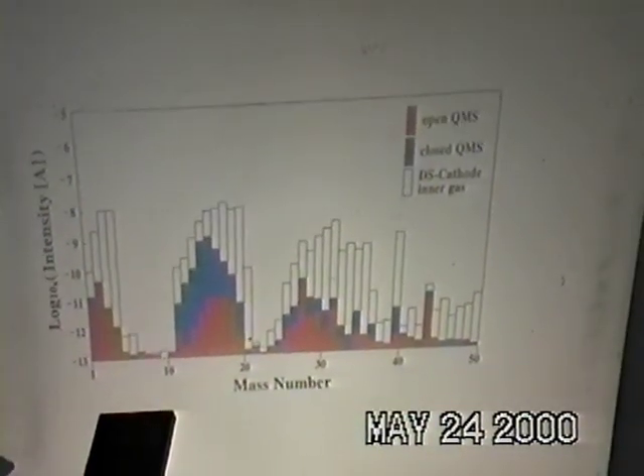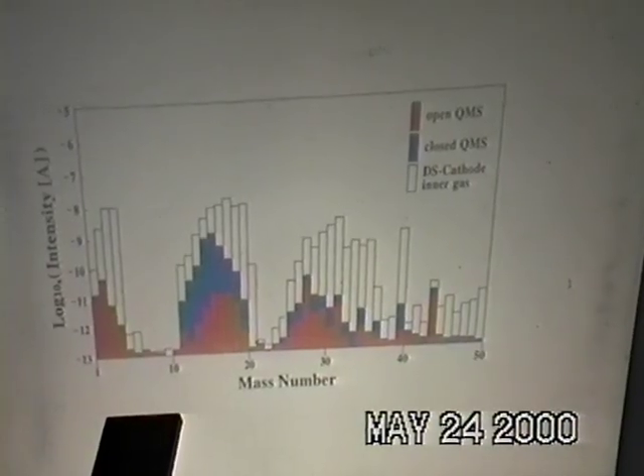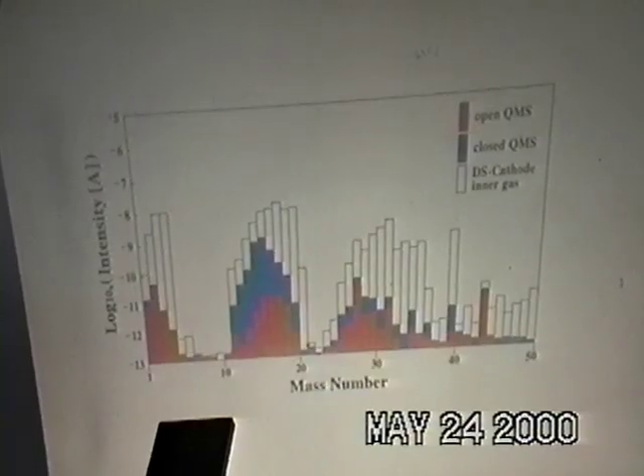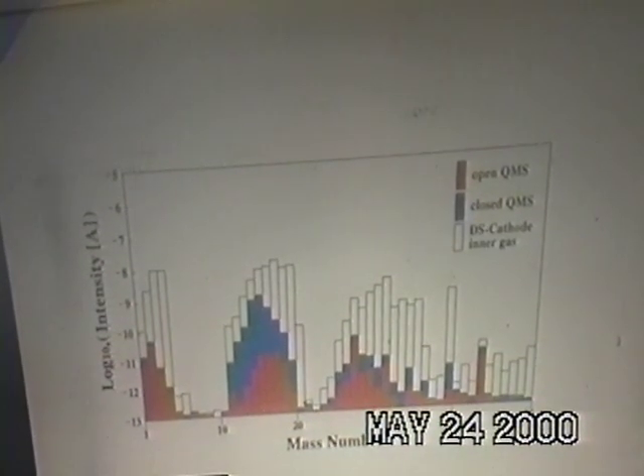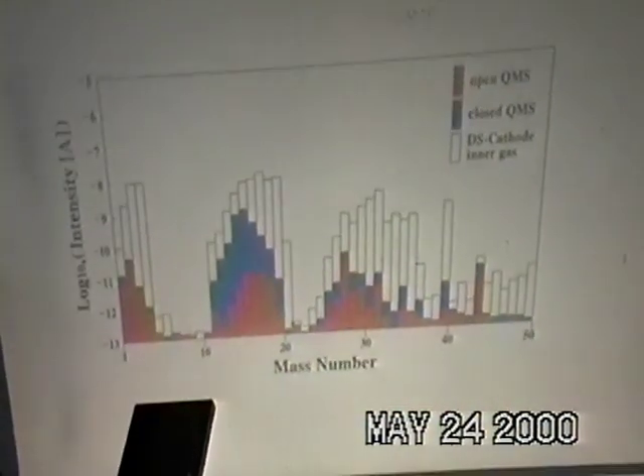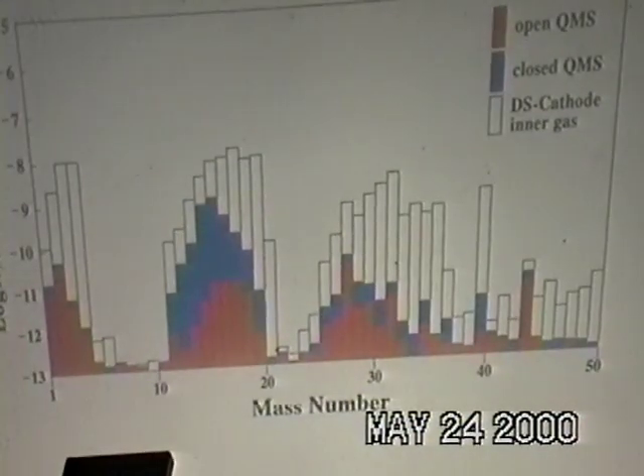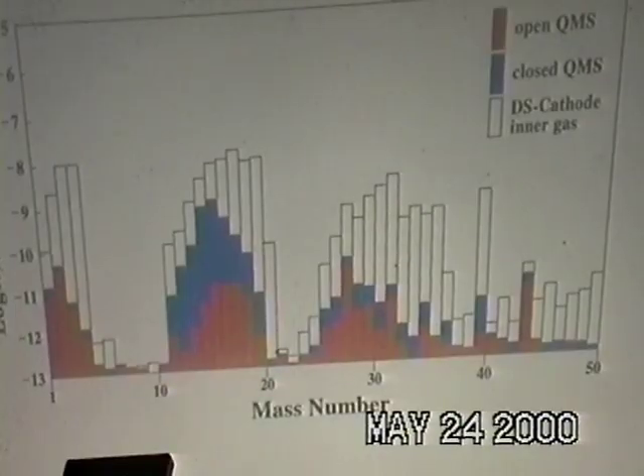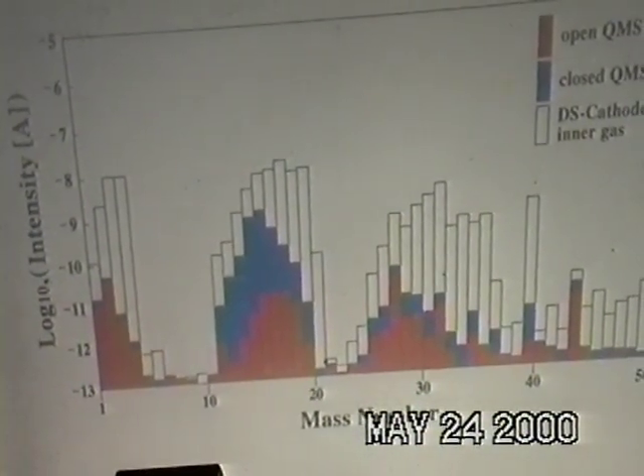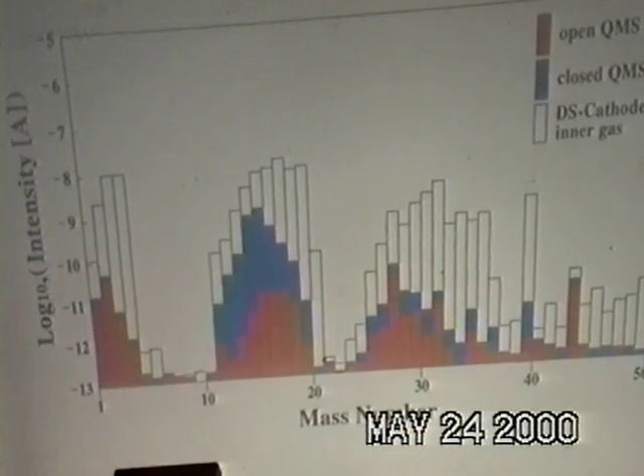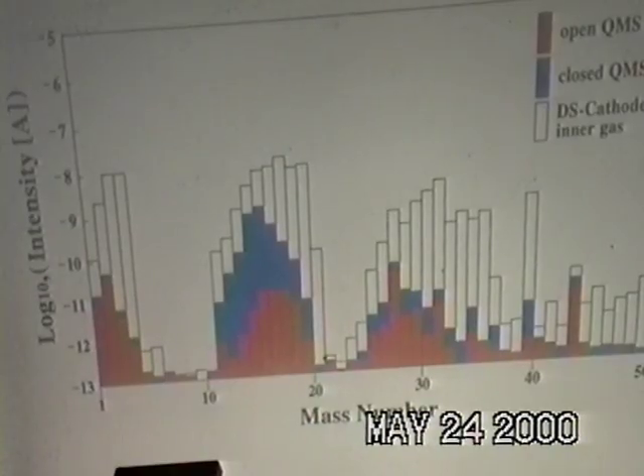This is a bar graph and demonstrates the basic characteristics of our developed closed QMS system, where the mass spectrometer range is 1 to 50. The red bar shows intensity distribution at the mass number using the open QMS system under a condition of 10 to the minus 9 torr during pumping action. The blue bar shows characteristics of the closed QMS system, and the open bar shows the inner atmosphere generated inside this cathode within the closed QMS system. This demonstrates the existence of enormous deuterium and much helium inside this cathode. And furthermore, it was confirmed that the function of our QMS is essentially fixed.